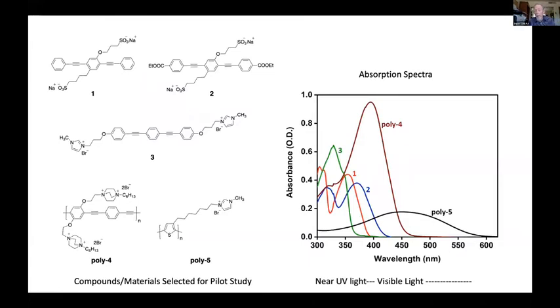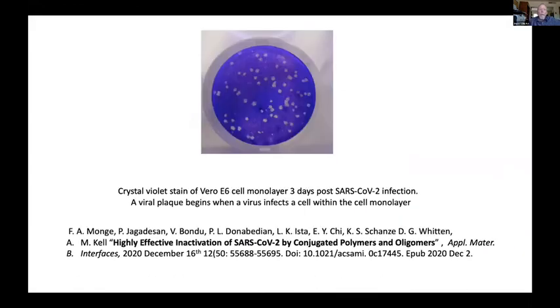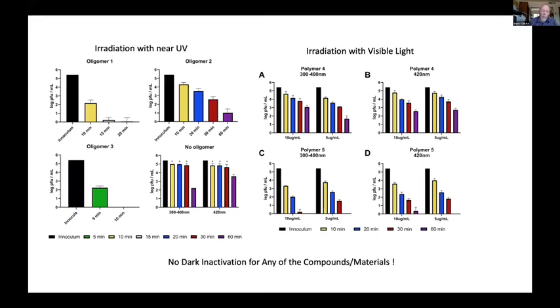We found there was no inactivation of the virus in the dark, but nonetheless, our materials were very, very active in the light. We used a crystal violet stain on another cell that is attacked by the virus. Wherever the cell is stained, you see it, but wherever a virus attacks it, you get a bleaching. Just to cut to the end, we found that with our oligomers and polymers, all 5 were active, but some were much more active than others. For example, here we have about 3 logs of inactivation after 5 minutes. Here with another one, we get 6 log inactivation after 15 minutes. But all of these are active, and we're very excited about this.